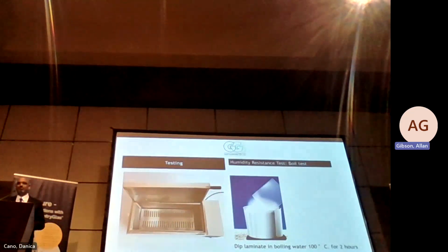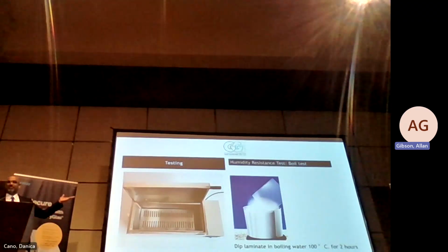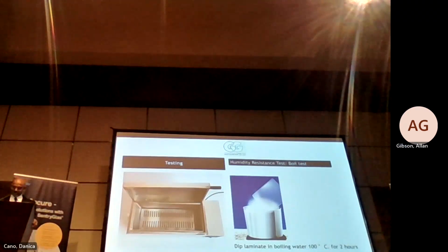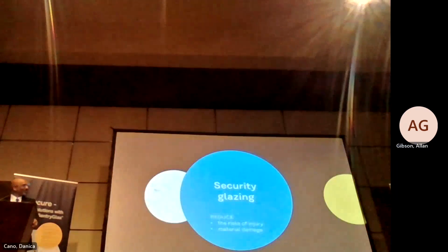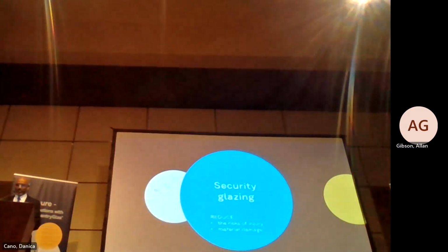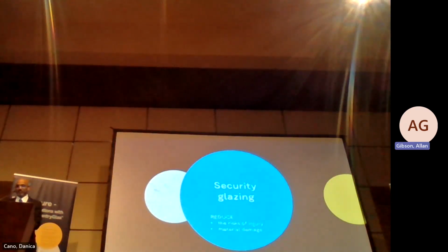This is an easy test. Just in summertime, take a bucket of water, it is already 100 degrees, put your laminate in and check it out. So that's the boil test. You just put it in the hot water for 2 hours. If you see bubbles, make your claim. Next.